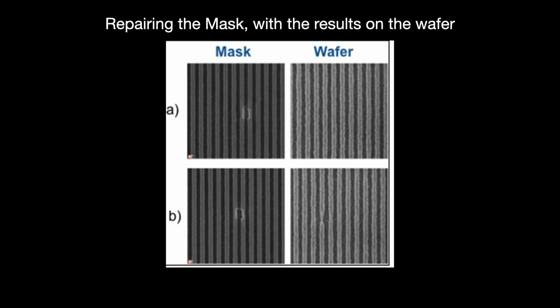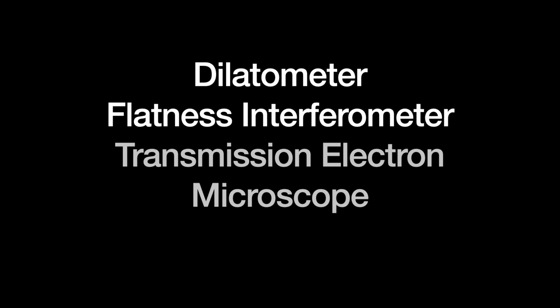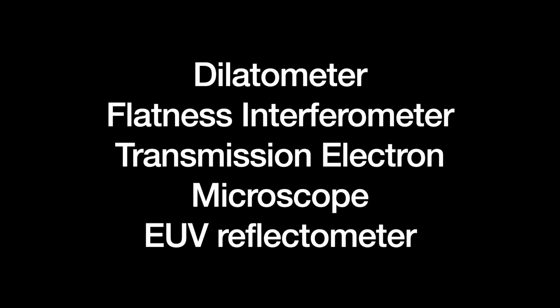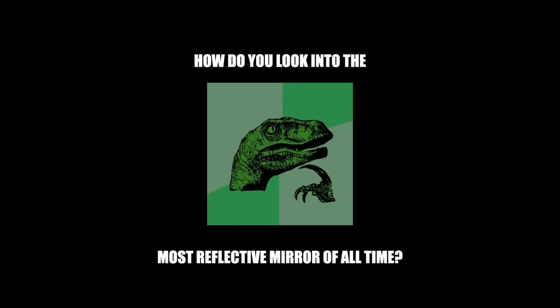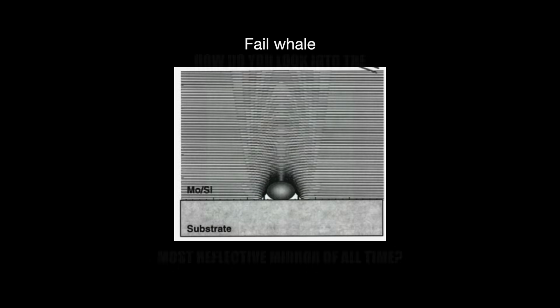Between the P37 and P38 standards, there are over 30 separate specifications that the EUV mirror has to meet. Relevant tools to measure them include the dilatometer, flatness interferometer, a transmission electron microscope, and an EUV reflectometer. The big problem is that many current instruments are not sensitive enough to detect when things go wrong. The extreme nature of the technology contributes to the difficulty in inspecting it. For instance, trying to probe the mirror layer's structures for defects is exceptionally challenging because, well, it reflects really well.